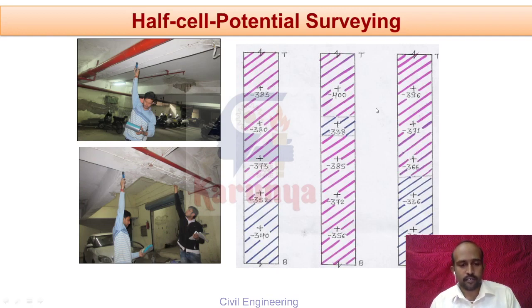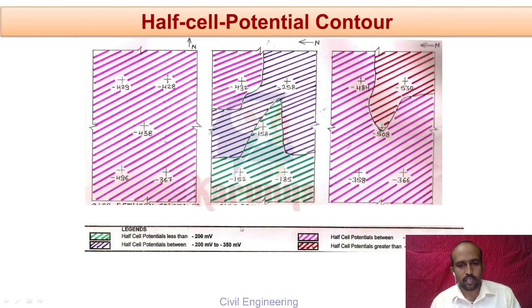So this graph shows the entire analysis of a particular beam. Finally we can plot the contour plots, then we can see which region is highly corroded and which region is less corroded. This is a typical contour that shows the corroded regions. Obviously the higher values, like minus 152, mean no corrosion. These are very low values, minus 508, minus 484, and the corrosion may be expected to be very high, minus 530 and so on. So let me show one video to understand this half cell potential meter better.